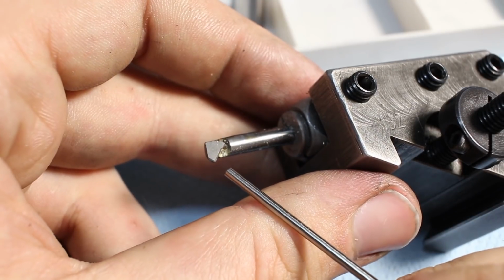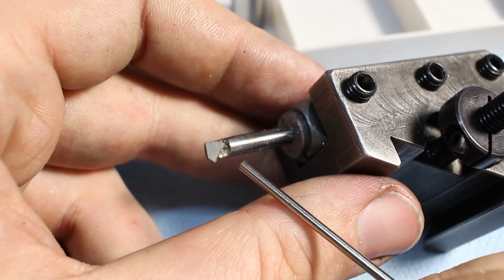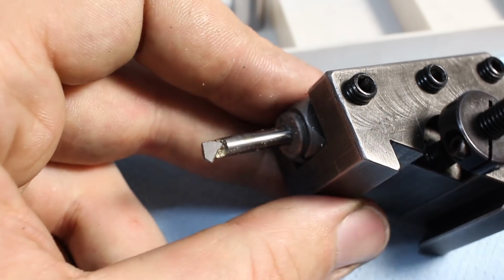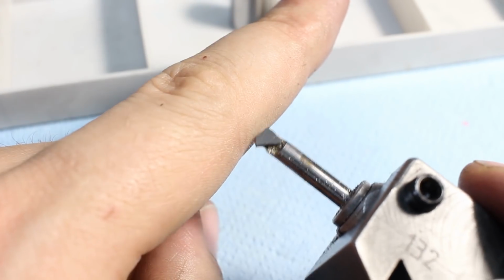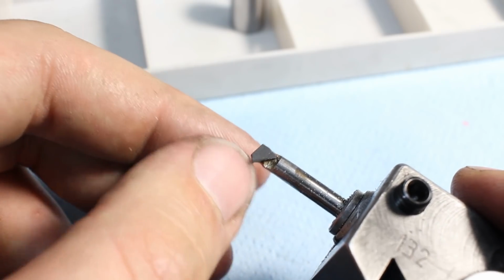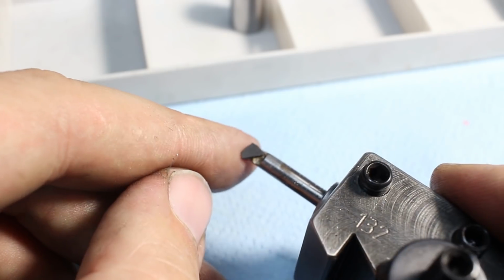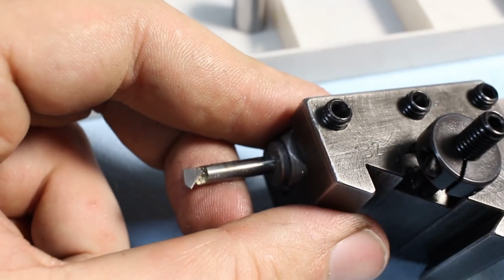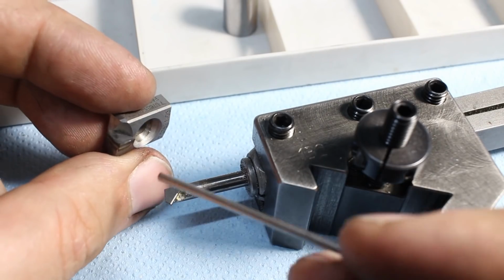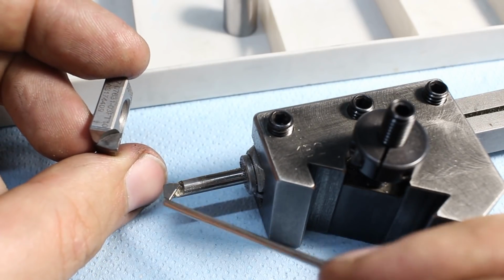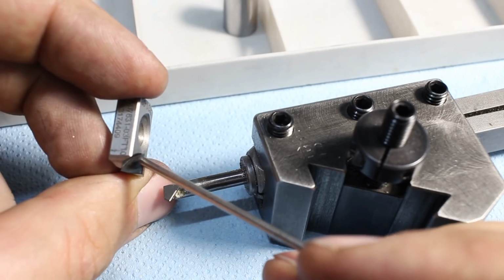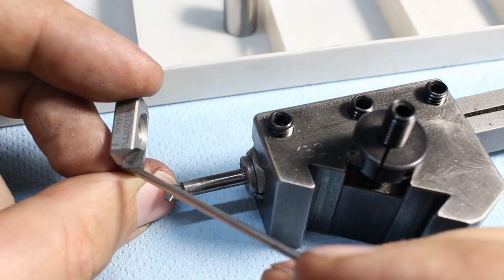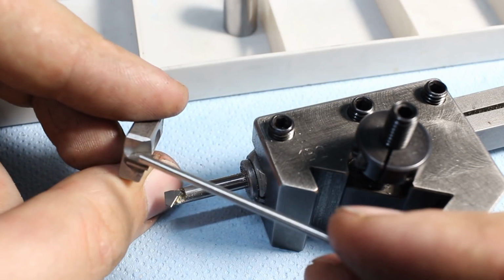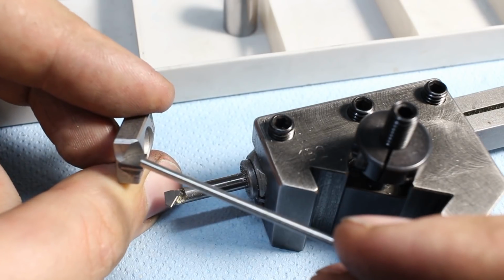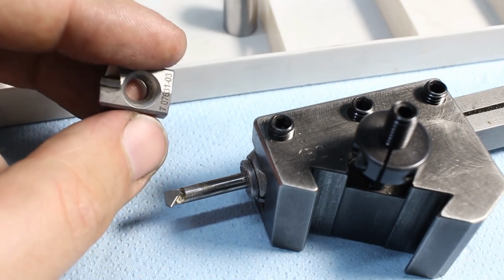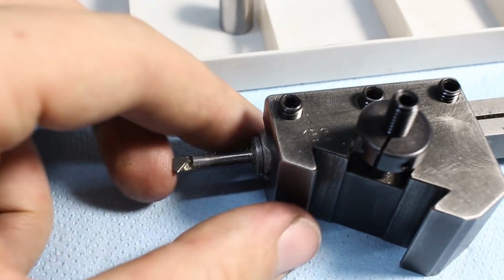You cannot really use a cast iron or aluminum or copper lap for lapping tools like this, because when you present it to the lapping disc, which is relatively soft material if it's not ceramic, the cutting edge will dig into the lapping disc and create havoc. So that's the reason why a ceramic lap is a good idea. CBN in general is ground neutral and has a tiny negative rake edge break. I think it's called a K-land. If you grind it positive or even neutral, it usually doesn't stand very well. So that's the magic behind CBN.